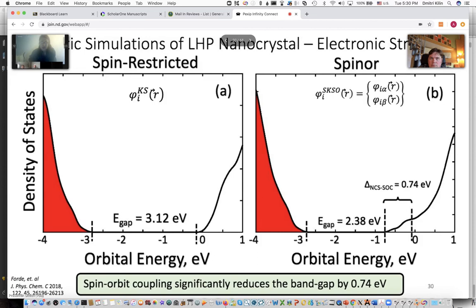And so just to compare the difference in the electronic structure between conventional or spin-restricted DFT and the non-collinear spin orbit coupling calculations on the left. If you don't include spin orbit coupling, you get a band gap of 3.1 eV, and then the density of states. Whereas if you include spin orbit coupling, the band gap shrinks to 2.4 eV, so it decreases by about 0.7